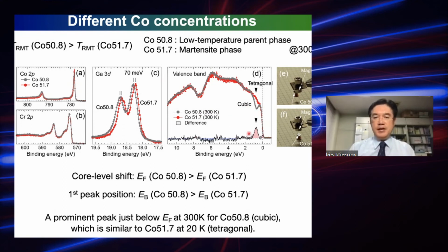So, the prominent peak near the Fermi energy at 300 Kelvin for the cobalt-poor sample is similar to that for the cobalt-rich sample at low temperature.